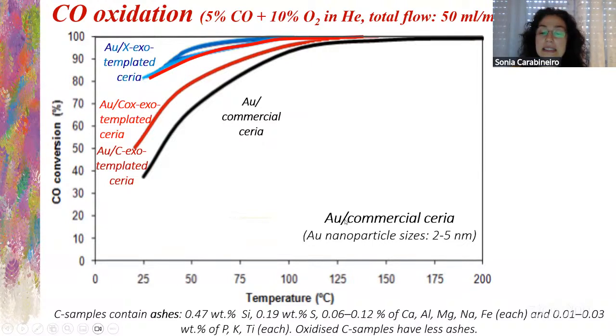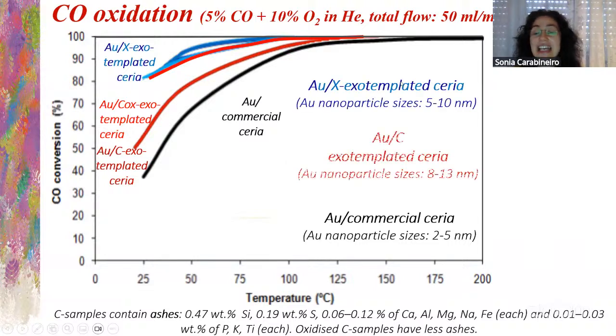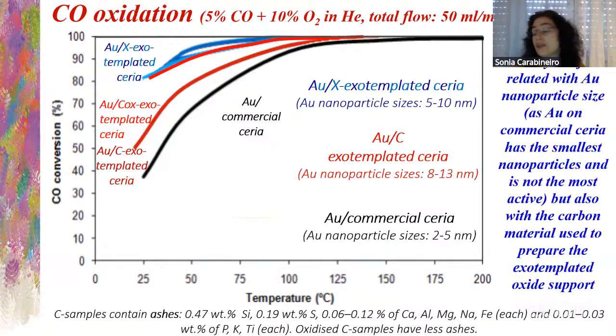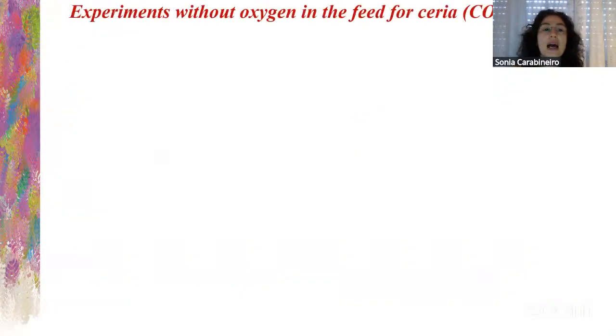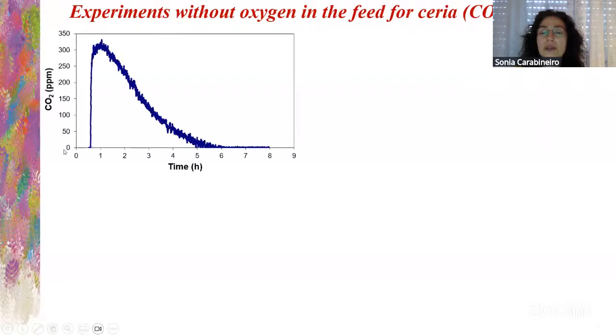If we compare the gold nanoparticle size, on commercial ceria they have the smaller gold nanoparticle sizes. However, they are not the most active. You see here, these sizes are larger than on commercial ceria. However, they are more active. So it's not only the gold nanoparticle size that matters. The activity is not only related to that, but also to the type of carbon material used. And usually the ones that have better reducibility of oxygen also have better results. Here we performed the experiments without oxygen in the feed for the CO oxidation. This is just the ceria material.